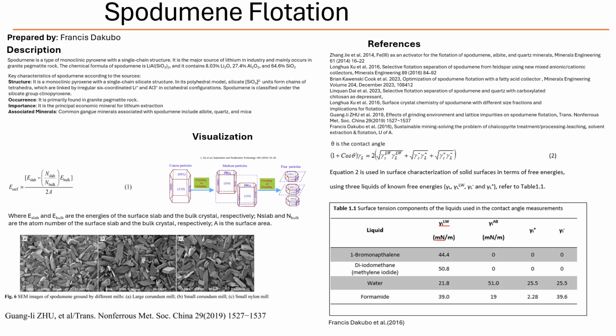Good question. The models also looked at that. What if a lithium or aluminum atom is just missing from its spot in the lattice? The calculations indicate these vacancies, especially if they're right on the particle surface, can dissolve pretty easily when in contact with the flotation solution. And that would change the surface. Potentially, yes. It could alter the local chemistry right where the collector needs to attach, which could impact the flotation efficiency. Okay, so we've got grinding effects, surface ions, internal impurities, even missing atoms, all influencing things.